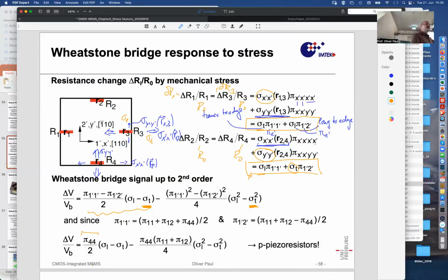And then the membrane needs to be endowed so you can produce some P resistor membrane. That pi coefficient is something like 138 times 10 to the minus 11 per Pascal. It's a substantial coefficient. And here we have the product of two coefficients, so the large one and then this small thing. So it's not from the same size as this object to the square. It's even much smaller. So the nonlinear response is suppressed by the fact that these pi coefficients of P silicon are quite low. But the conclusion that we need P resistors is, of course, unambiguous.